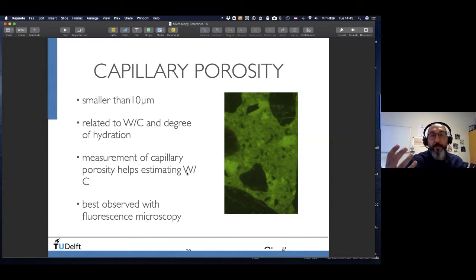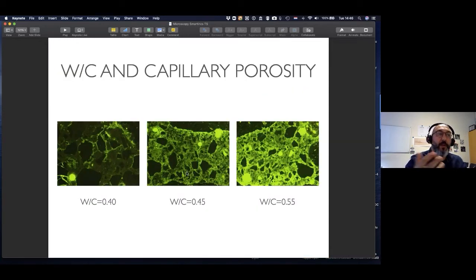If you see a lot of green light coming out of our cement paste, then we can say, hey, we have high capillary porosity. And if it's very dark, you can assume that it's a low capillary porosity. And by correlating the amount of green light you're observing to some other properties, such as water-cement ratio, you can easily estimate, for instance, the unknown water-cement ratio of an unknown concrete. So you observe here the effect of capillary pores under the UV light microscopy, fluorescence light microscopy. It's a more proper term. You see the lower the water-cement ratio, of course, the lower the capillary porosity.